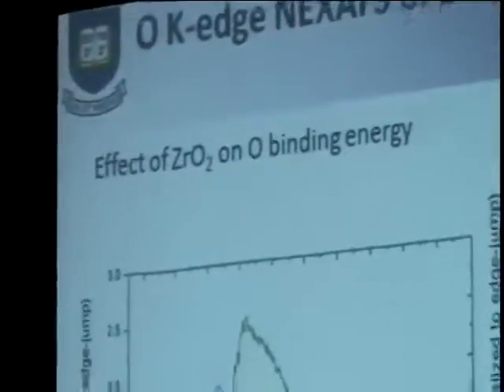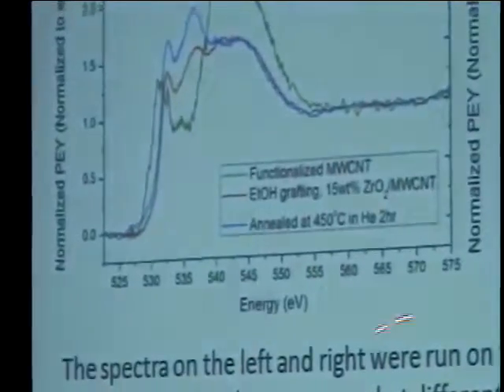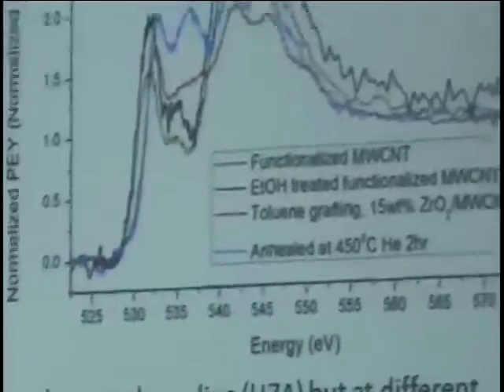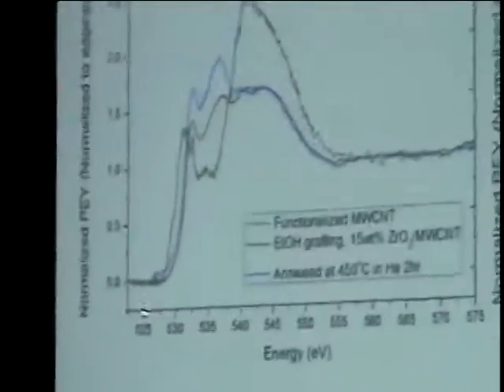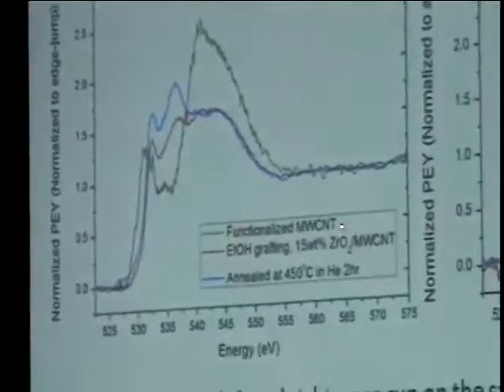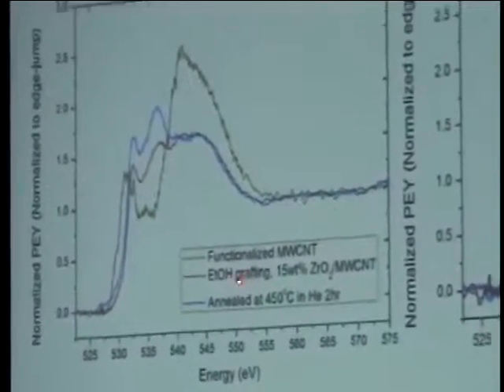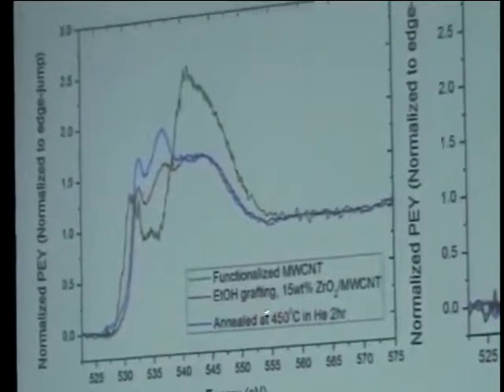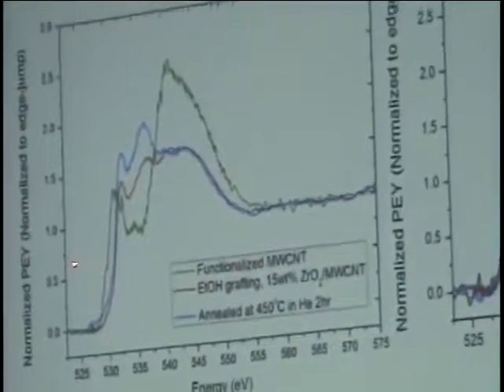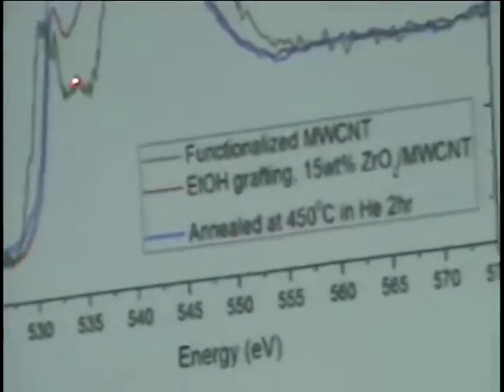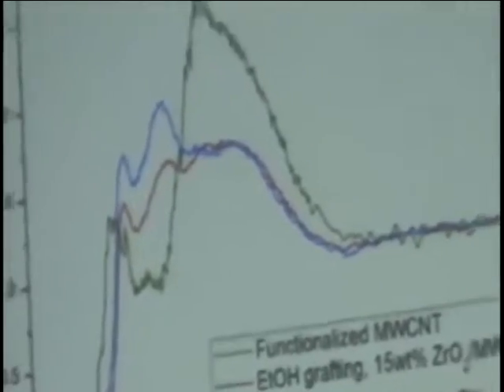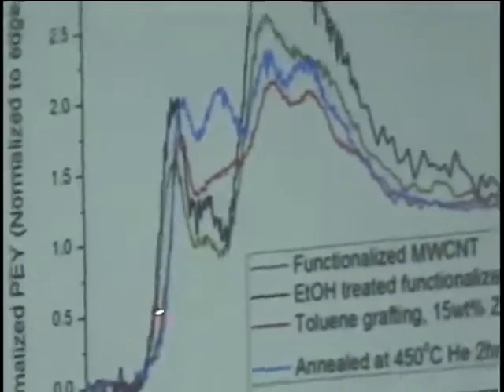And how we're looking at 2 examples. These are oxygen K-edge absorptions. They're kind of dense, 2 kinds of spectra here, but I just want to draw your attention to 2 things. Over here we have the leading edge, which is at lower binding energy, for functionalized carbon nanotubes, or functionalized carbon nanotubes which have been reduced by ethanol at high temperature in the liquid phase. And they are lower binding energy than when we have zirconia, which is shifted up. Here we've got the same situation, where we've got a functionalized carbon nanotube, and then again one that's been reduced in ethanol, and relative to zirconia, where the carbon nanotubes have zirconia on them, there's a shift.